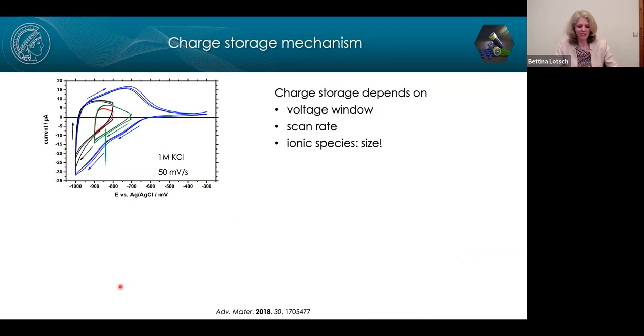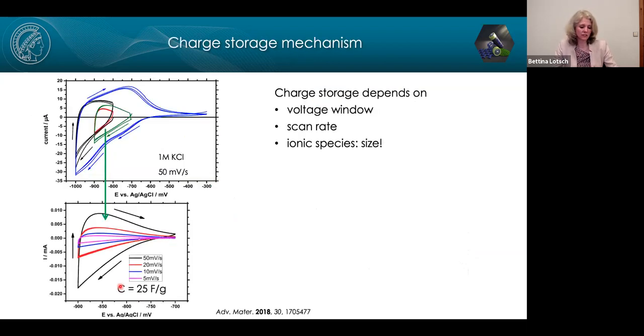Now, we're still struggling to understand really the nature of charge storage in these systems. So I cannot really give you a conclusive or final description here. What we can see in these cyclic voltammograms is that charge storage depends on the voltage window. I guess that's also not too surprising, and the scan rate. And that clearly shows us that we have different contributions, capacitive and also Faradaic or pseudocapacitive contributions to the charge storage. And it's most likely a combination of the two, but the dominant one we believe is a pseudocapacitive, diffusion limited charge storage, so a rather slow process. Nevertheless, it's kind of a hybrid system.